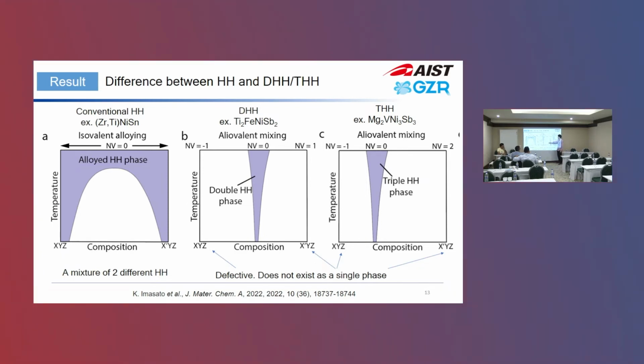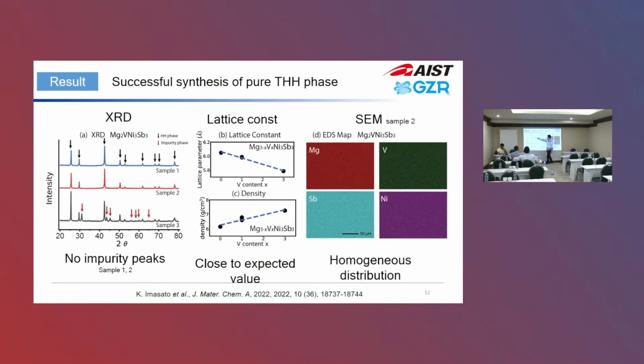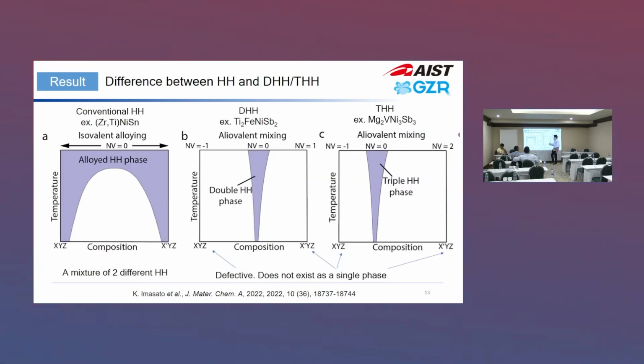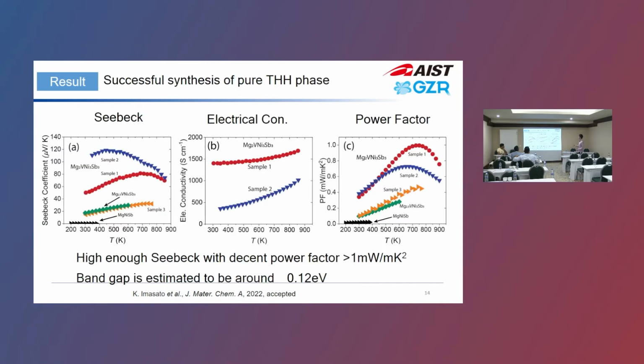Probably yes, but probably not. The double Half-Heusler phase itself is a single phase even at 0 K, and they have a different crystal structure and ordered phase. Actually, we didn't see the ordered structure here. This is just a Half-Heusler phase, completely disordered on the magnesium vanadium side. But by this phase diagram definition, conventional alloyed ternary Half-Heuslers are different from this kind of single phase disordered structure. So that's the crystallographic and materials scientific definition of the double Half-Heusler versus conventional alloyed Half-Heuslers.